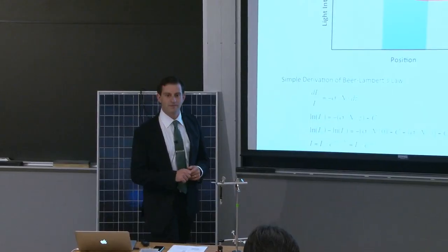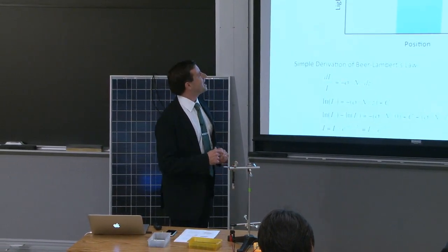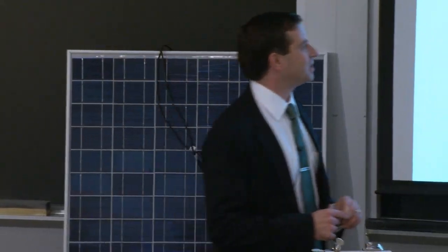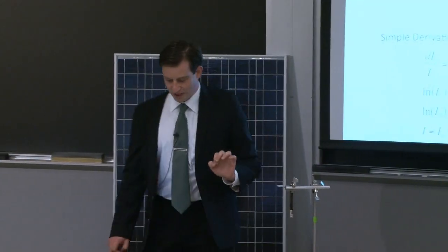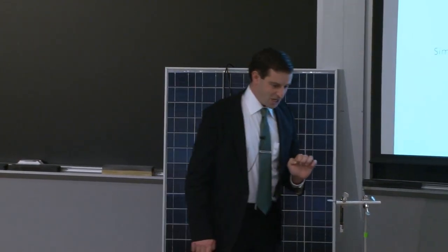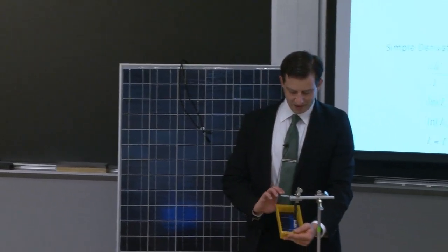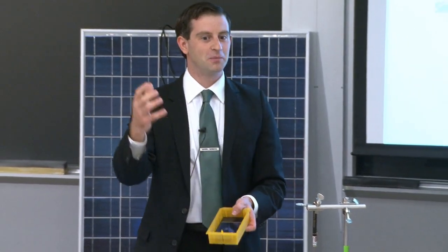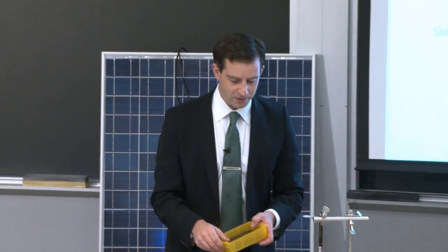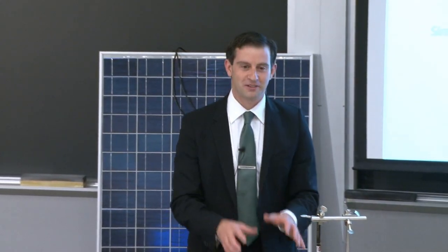It's called an absorption coefficient, but is it more of an extinction coefficient? Really, it seems kind of confusing that it includes scattering. So the extinction coefficient, absorption coefficient, yes, in solar research, when we talk about an absorption coefficient inside of a material, oftentimes we're operating in a wavelength regime of light wherein free charge is excited. But we can also keep increasing the wavelength of the light, say out to 10 microns, very long wavelength, very low energy light. And that can excite free carriers within the material, carriers that are already excited, essentially exciting them further without generating any new free carriers inside of a material. So we won't necessarily be generating more current by shining light on it, but we'll be absorbing light nevertheless in our material. So it's important to keep the underlying physical processes that are occurring distinct.